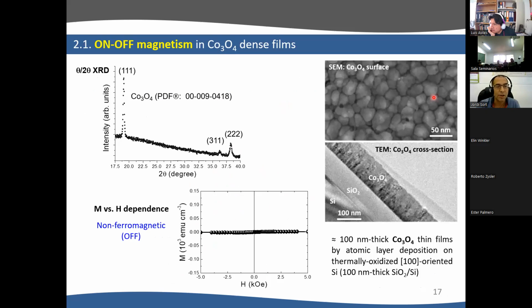But first of all, here is a characterization of the as-grown cobalt oxide dense films. Actually, they were about 100 nanometers thick. So you can see here that we are not limited to 2 nanometers as in the works of charge accumulation that I've shown before on iron platinum or iron palladium. Here the layers are relatively thick and there is a columnar growth. They are polycrystalline. You don't need epitaxy. Actually, grain boundaries here are good.